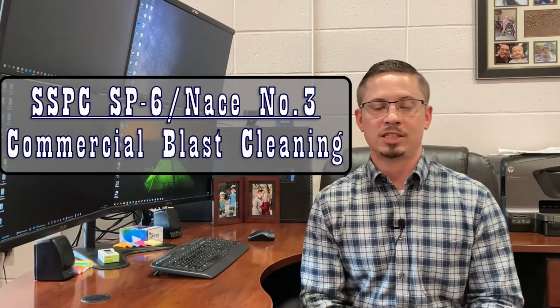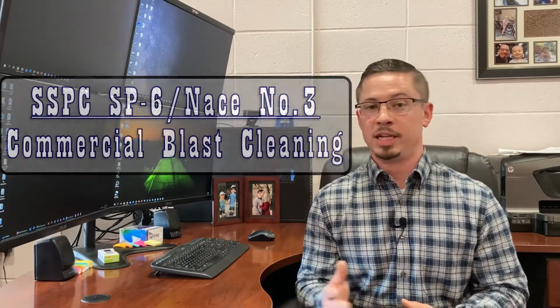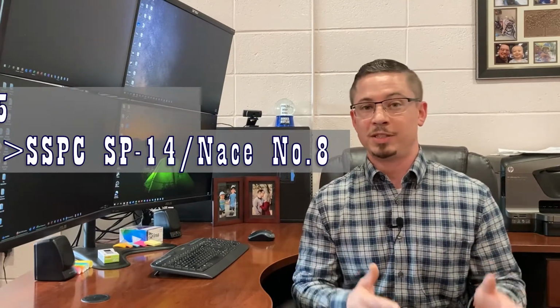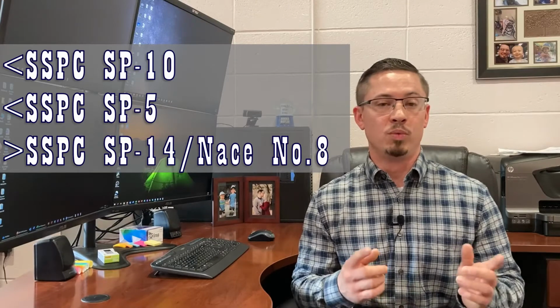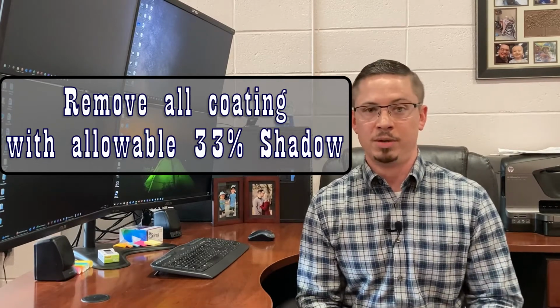SSPC SP6, or NACE number 3, is commercial blast cleaning, and it's also a very common requirement. It's not quite as lenient as SP14, which is NACE number 8, but it's nowhere near as restrictive as SPs 5 and 10, which are NACE numbers 1 and 2. This standard also requires the initial performance of SP1 solvent cleaning. Now, it does not require that you get down to what's called white or near white base material, but you should remove all coatings and contaminants with an allowable 33% shadowing.